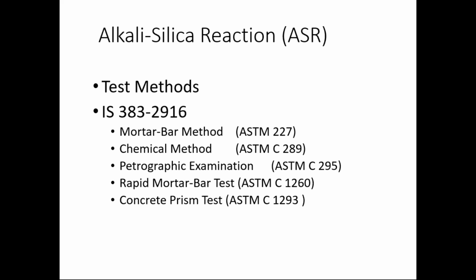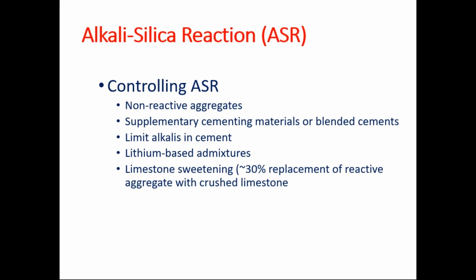Petrographic examination is really important to know the mineralogical composition of the aggregate, so that we know whether it contains any reactive silica or the clay particles in the coarse aggregates. Then by accelerated method, by rapid mortar bar method, we can also find the alkali silica reaction. Concrete prism test is important because all other tests are done on mortar samples, whereas concrete prism test is one test which is done using the concrete sample, so that will be more realistic and more useful test to find out the alkali silica reaction.